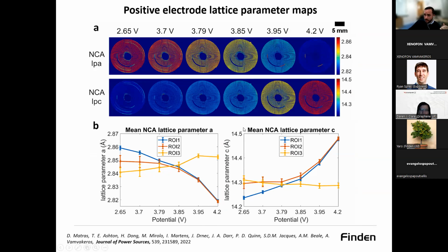We can also look at our cathode, or the positive electrode anyway. So this was the nickel cobalt aluminum oxide. Again, we can see that the parts of the NCA that are directly connected to the aluminum tab are totally inactive. It's the one that's called ROI 3, region of interest 3 here, the yellow one. And you can see the two parts that are red at the bottom figure. So the chemistry is not changing there, so nothing's happening to the NCA.